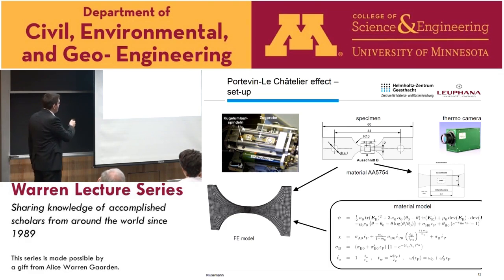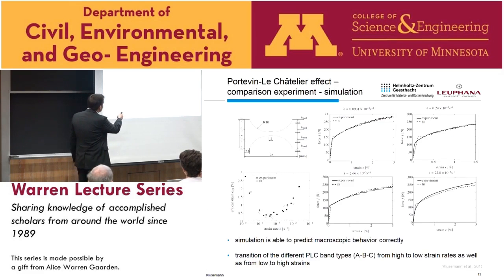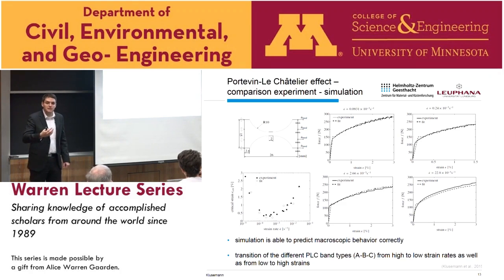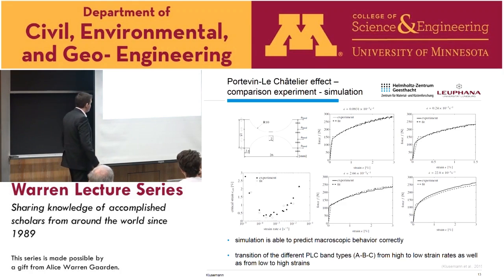So we identified our simulation based on experimental data for a number of different strain rates. And what you can see here is that from the very low strain rate, where you have a very oscillatory behavior, it gets much more to this kind of step-stair structure. And this is also predicted by the simulation accordingly.